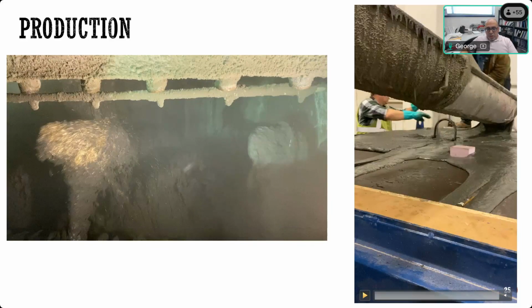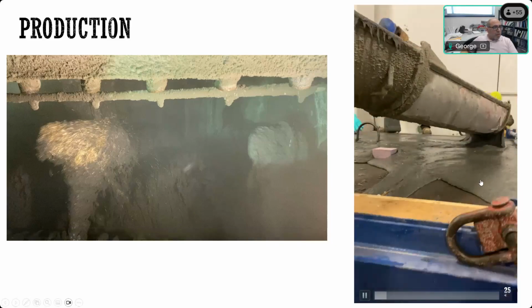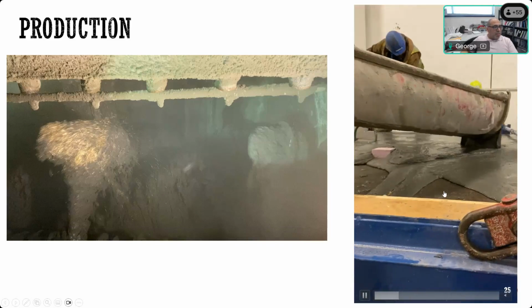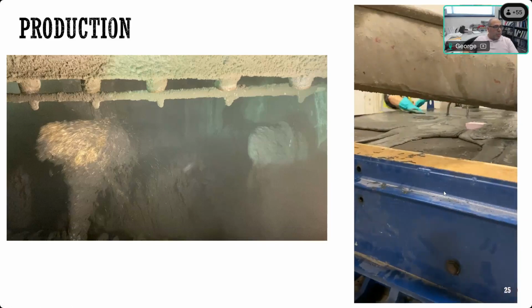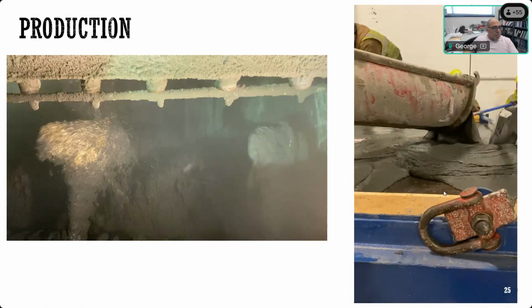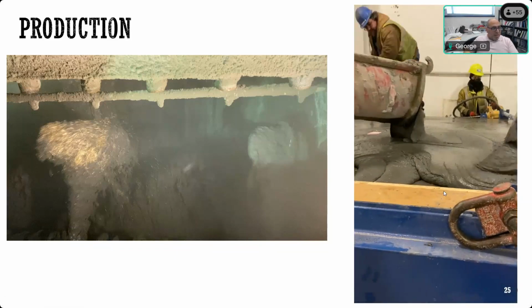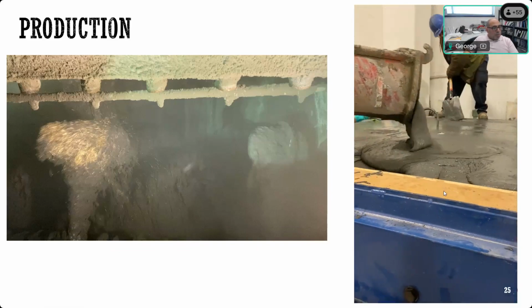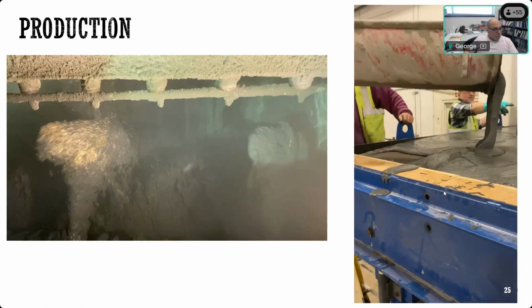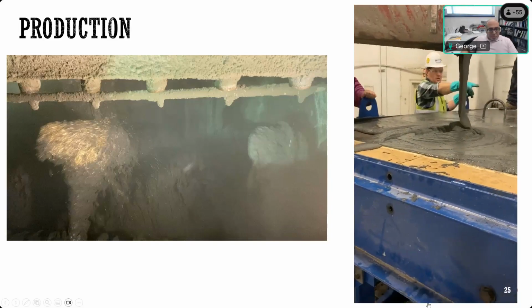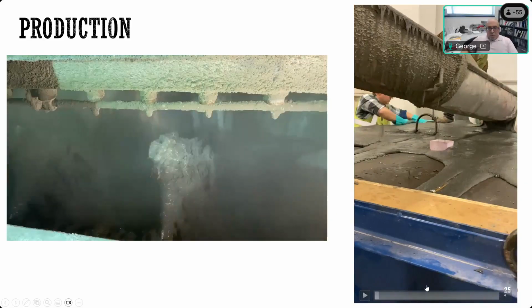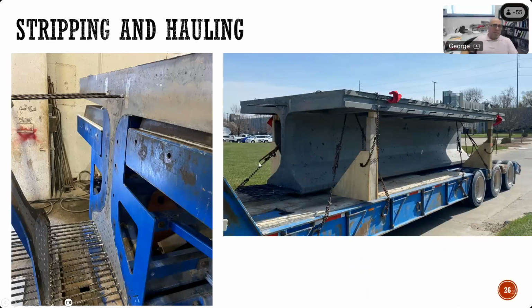Here's another one that shows when they were casting it, showing how flowable it is, and it can fill the bottom flange, the web, and then at the top it filled the ribs between the pans. So it's a very stable and very workable mix. So this is a segment that was produced, with the pre-tensioning strand at the bottom, dropping the top flange form, dropping the pans, and then shipping it to the lab for testing.